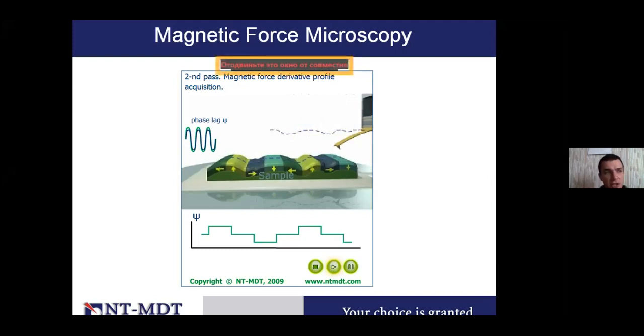Because the repulsion force, adhesion force, and van der Waals force will be much stronger than magnetic forces. But going far away from the sample, at a distance of maybe 100 or 200 nanometers, there will be no such forces, and only long-range forces will act between tip and sample. So in that way, during the second pass, we can measure the magnetic properties. And a technique like magnetic force microscopy always operates in two passes, just to avoid the influence of the topography forces, let's say.